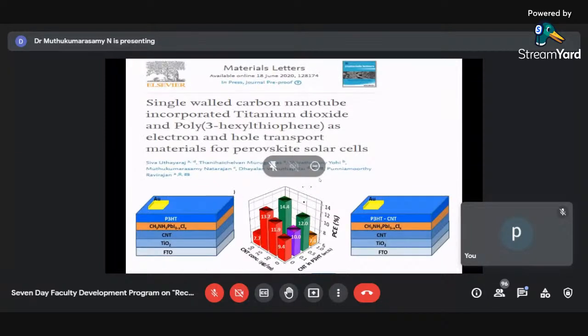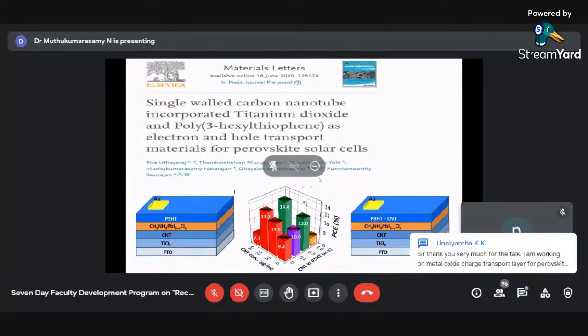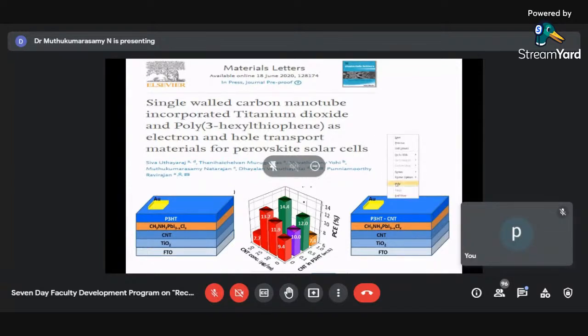These were all done in 2018, 17, etc. Then in 19, we were able to introduce carbon nanotubes also: single-walled carbon nanotube incorporated titanium dioxide. It was introduced into the perovskite material, into the hole transporting material, and into the electron transporting material. We even used carbon nanotubes as a hole transporting material. We were able to achieve an efficiency of nearly 15% when we used carbon nanotubes both in the perovskite material and in the hole transporting material.